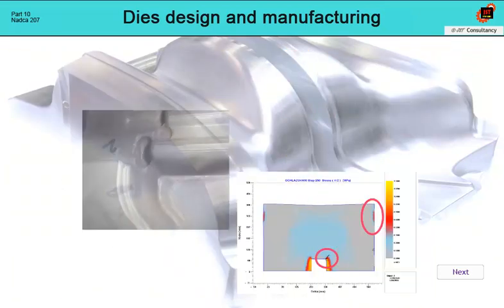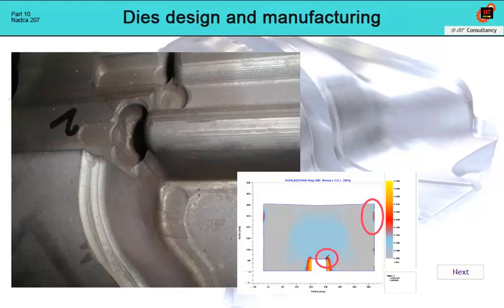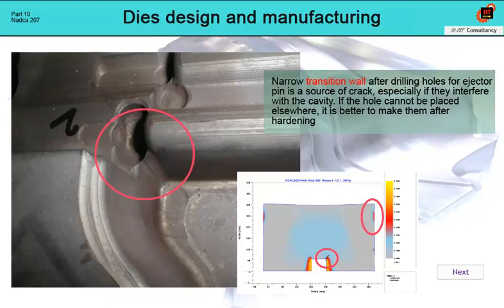In this case, the designer chose a drilled hole, probably for the ejector pin, that touched the cavity and creates a thin transition wall on the die. As this thin wall cools first, tensile stress develops in it, leading to the formation of a crack. If it is not possible to move the ejector pin hole further from the cavity, it is better to make this hole after hardening. It will be more expensive but safe for heat treatment.